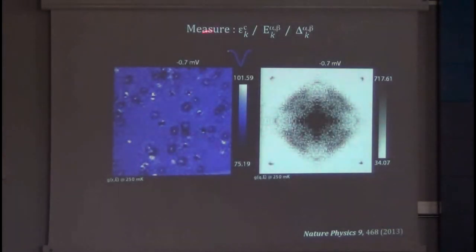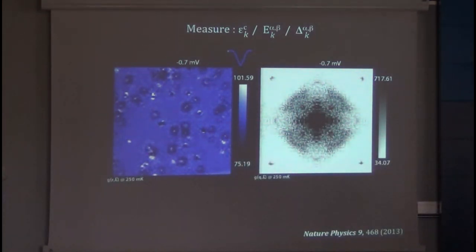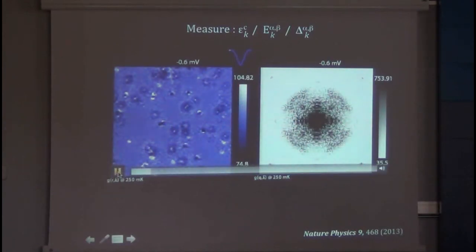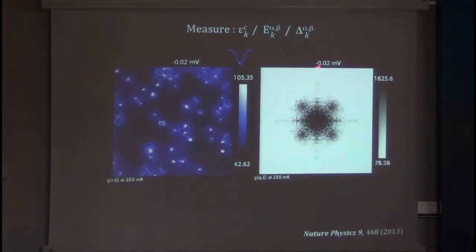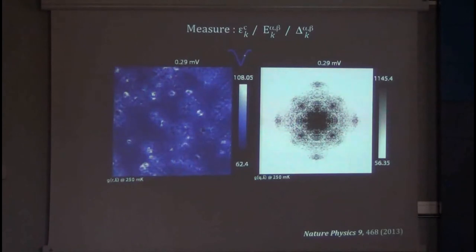So here at last are the Bogoliubov quasiparticle wave function images. And now the step size of these images is only a few tens of microvolts. But nevertheless, we have a complete map taken at low temperatures. This map was really challenging to get, all the data. But you can see the heavy Bogoliubov quasiparticles here. An expert can see that this is a nodal superconductor. We figured that out instantly.